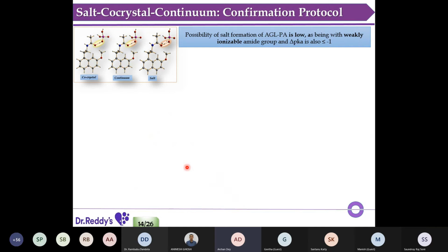So here you can see that this molecule is an amide, which is not generally an ionizable group. And if you look at the pKa, the pKa of agomelatine and phosphoric acid is -1. So it's near to impossible, according to the delta pKa rule, that it can form a salt. But there was some symposium literature. Without publishing a crystal structure, they were calling it an agomelatine salt. That triggered us to look in more detail.